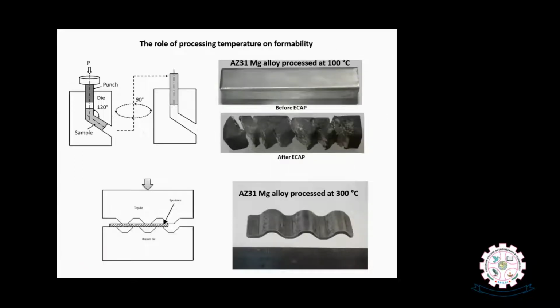For example, if you consider AZ31 magnesium alloys, when we conduct the plastic deformation at room temperature by using a severe plastic deformation technique called equal channel angular pressing at 100 degrees centigrade, you can see here before ECAP and after ECAP. Equal channel angular pressing is a simple solid state plastic deformation technique where we use mechanical loads to introduce huge amount of strains. What we call severe plastic deformation technique. After processing also, material geometry will be preserved, maintained. But we introduce huge amount of shear strain into the material by repeatedly doing a number of cycles.